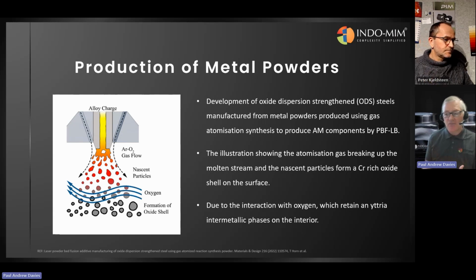This is quite a relatively new concept of passivation of powder particles, especially from an oxide dispersion strengthening point of view. And it seems prevalent in other materials as well. So, for instance, aging steels and even stainless steels, as printed by laser powder bed fusion, tend to have higher mechanical properties than wrought materials until they're annealed. And this is often due to oxide dispersion and strengthening aspects, actually.